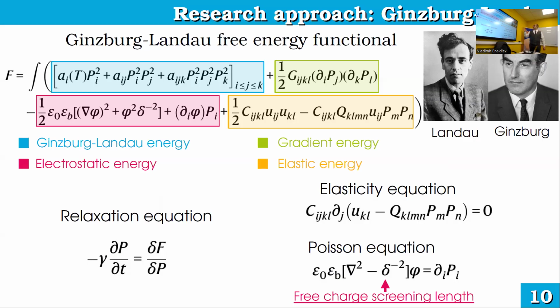Okay, so in our case, the Ginzburg-Landau free energy looks like this. We have four components. The Ginzburg-Landau energy itself, which gives rise to spontaneous polarization. The gradient term, which penalizes non-uniformities, but basically the gradient term gives you, for example, domain walls. And electrostatic and elastic terms. The electrostatic term gives, for example, the possibility to apply electrical fields. Also, of course, it's connected with this divergence of P. If you have some bulk charges inside the volume, you will get sources, and some destruction of your spontaneous polarization. Elastic energy allows for elastic coupling; if you want to simulate a thin film, you can apply the effect of the substrate on this film.